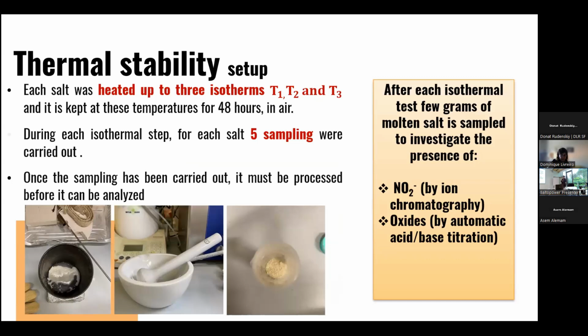So during each test, we insert the salt in the setup, and the salt was heated up to 3 isotherm values and is kept at these 3 temperatures for 48 hours in air. And during each isothermal step, we sampled the salt 5 times to analyze the salt during the time and according to the temperature. So after each isothermal test, a few grams were sampled, and we investigated by ion chromatography the presence of nitrites, and by acid-base titration the presence of oxides.